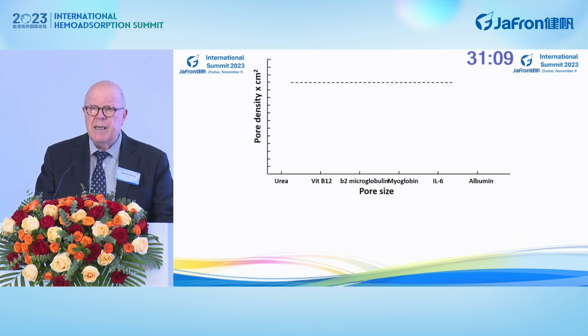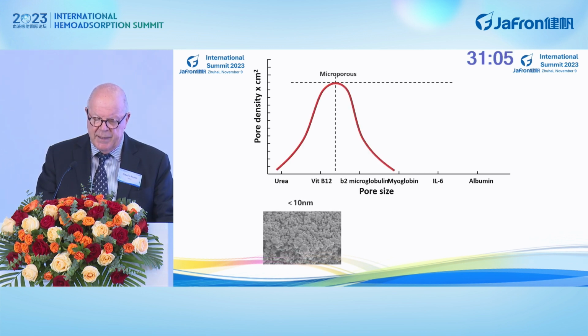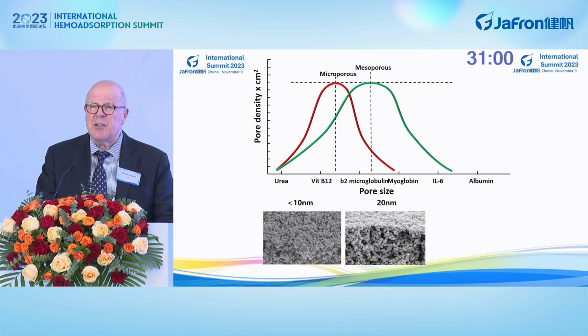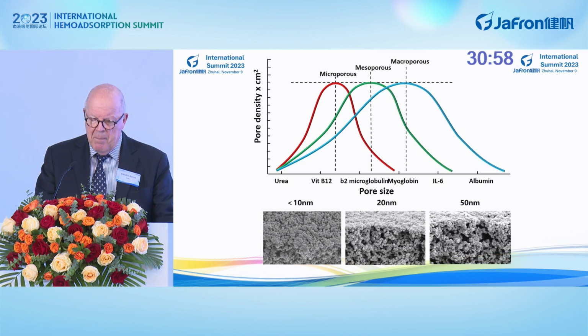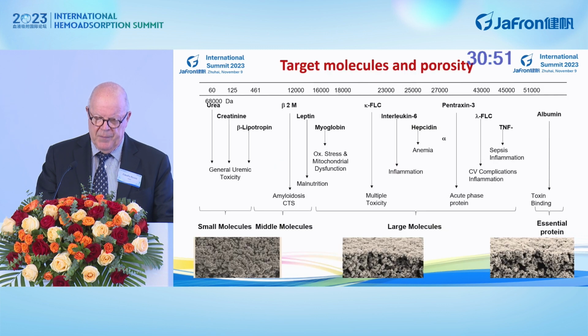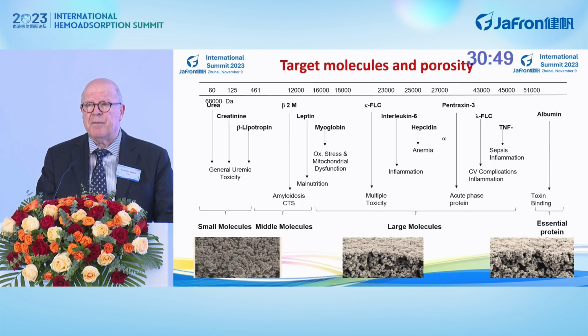So, if you see here the curve of pore density and pore size distribution, you may have a microporous, you have a mesoporous, you may have a macroporous, depending on the characteristic of the target solutes you want to remove. And here you see that different target molecules may represent small molecular weight toxin, may represent middle molecular weight toxin, large molecules, and even protein-bound toxin.